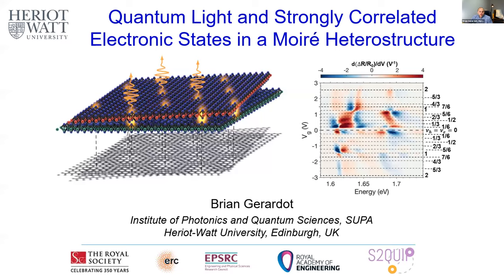And so the lattice mismatch for these two materials, which are the ones that our samples will be made of today, is about 0.4%. So they're very nearly aligned. So really the Moiré periodicity is primarily determined by the twist angle. So you can see here for about a 3-degree twist, the periodicity is about 6 nanometers.